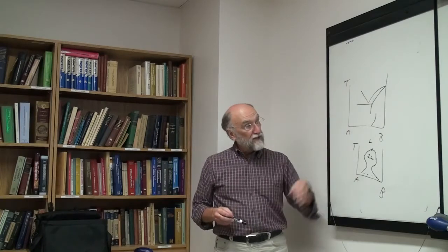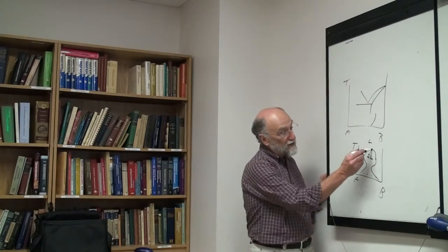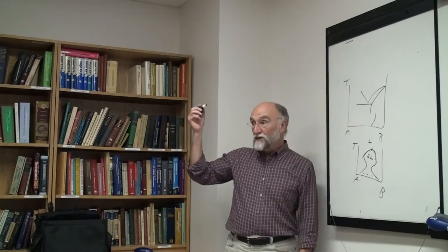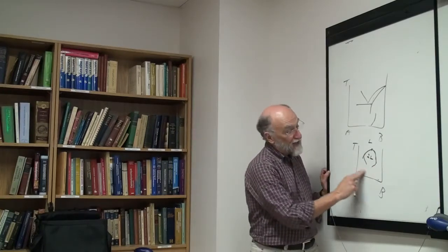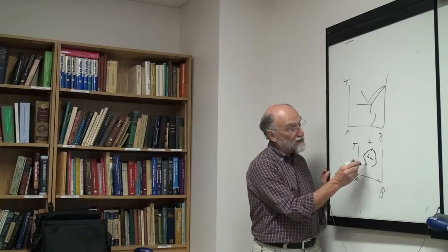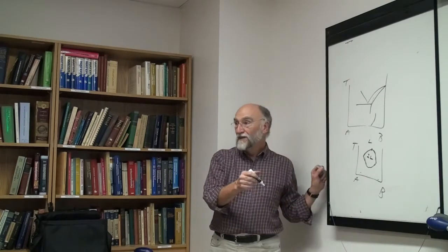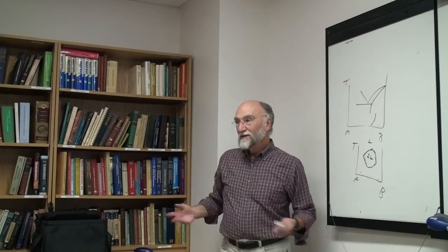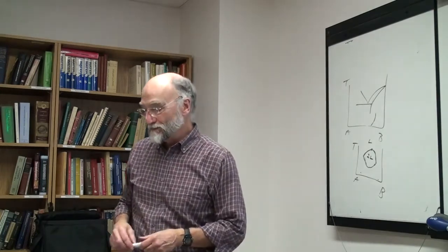Remember, you have a positive excess Gibbs energy here. But if the excess Gibbs energy varies so much that it becomes less and less positive as you go down in temperature, because of an entropy effect, then it's going to come back around again. So thermodynamically you can even see this, but they're considered curiosities rather than anything you have to worry much about.